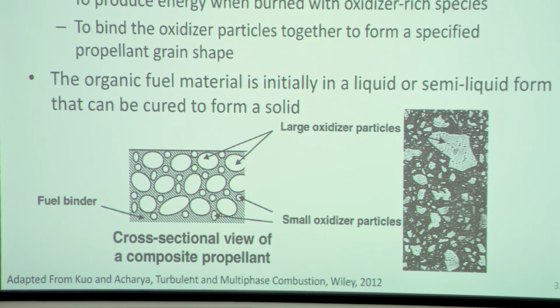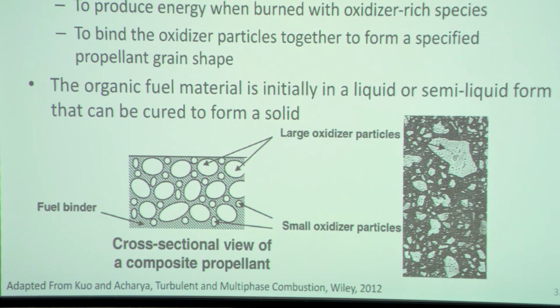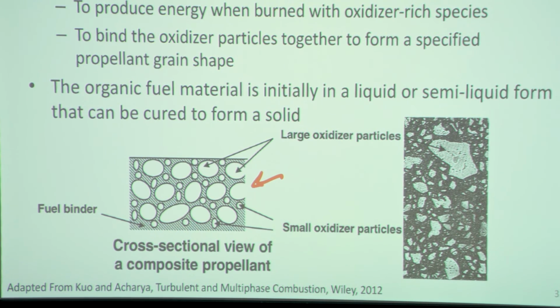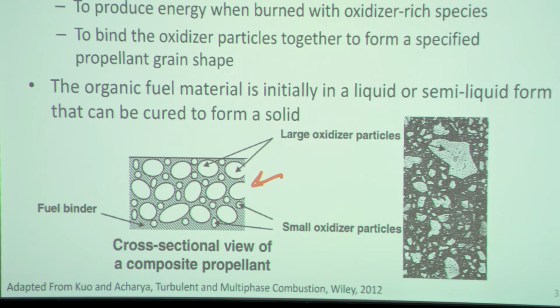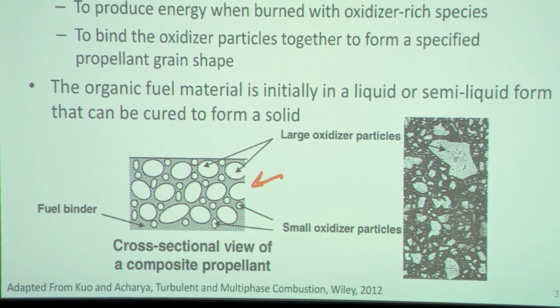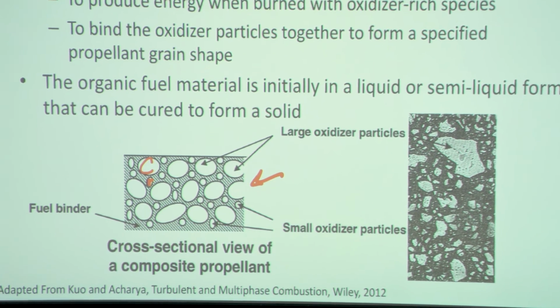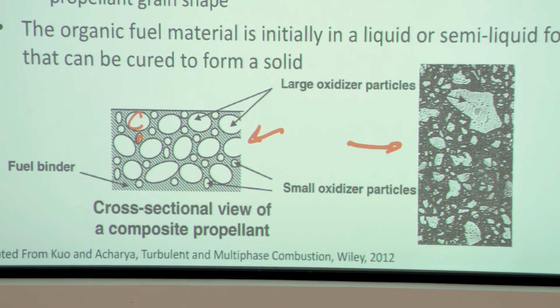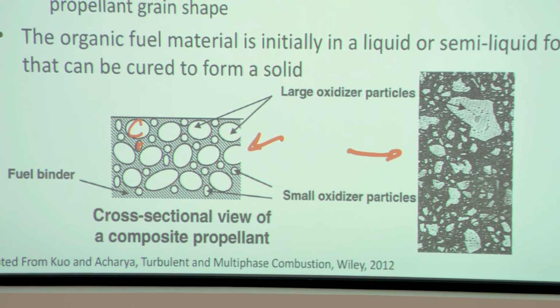Okay, and so the final product might look something like this, where I have a solid shown here, and in this particular case, I have oxidizer particles, and in this case, maybe they're ammonium perchlorate crystals of different size. So typically, I'll mix a distribution, at least a bimodal distribution, and sometimes a trimodal distribution. And that's for packing density characteristics. I want to get as high a solid loading of the oxidizer particles as I can. And so here would be the large particles and the small particles. And again, on the right here then is a micrograph of, say, an AP-HTPB grain.